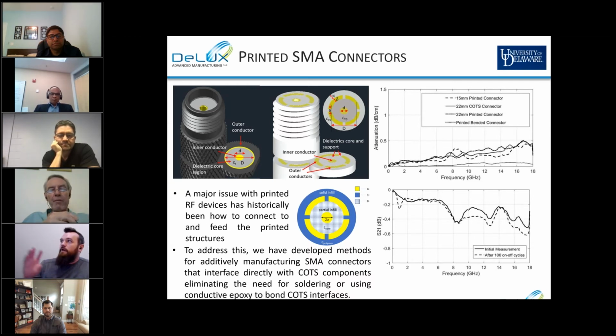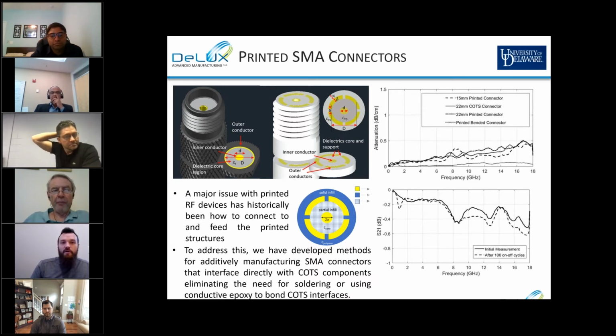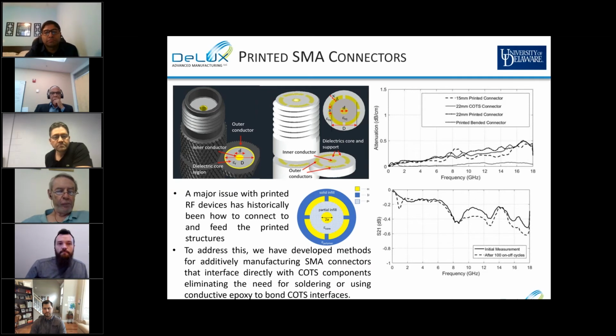So the first thing I want to talk about is our printed RF connectors. Like I said, it addresses a historically common issue that people have: they print an antenna, they print an RF system. How do you get signals in and out? A lot of times that means you take a commercial off-the-shelf connector, you conductive epoxy it on there, and you introduce a bunch of loss to your system and degrade your performance. So we decided to tackle that problem by developing fully printed connectors that you can integrate directly into your build, eliminate your need for soldering, post-processing, etc.